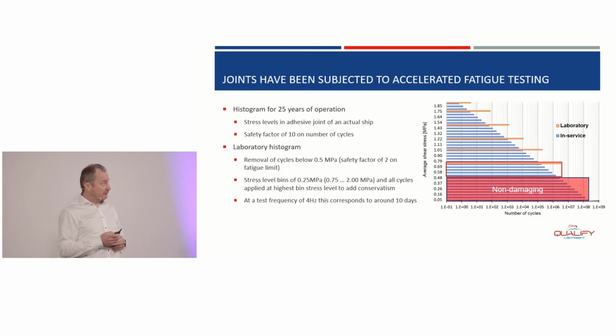Testing is done in fatigue. Luc already introduced part of this diagram. From Bureau Veritas, we got a load histogram representative for 25 years of operation of the ship, showing the stress levels reached at the joint. If you look at the numbers on the vertical axis, you see that stress levels in fatigue range up to around 2 megapascal. The number of cycles indicated at the bottom are 10 times more than what the ship sees in reality, so there's a safety factor of 10 on the number of cycles. Of course, we were already dealing with 25 years times 10.